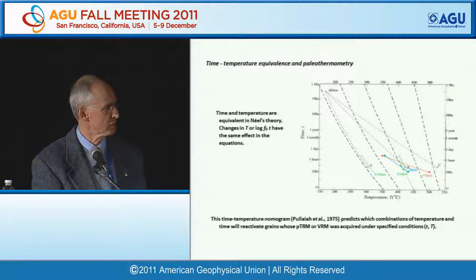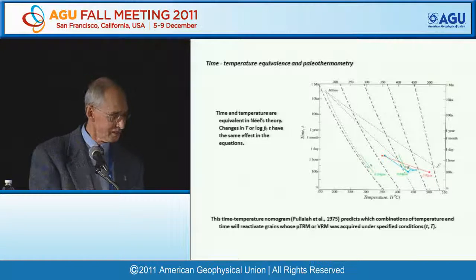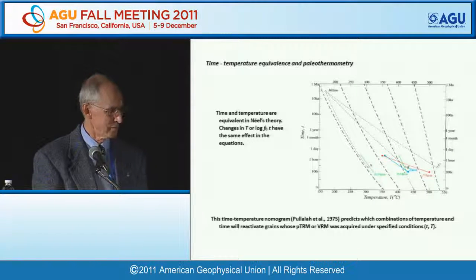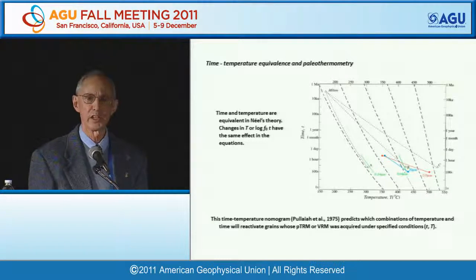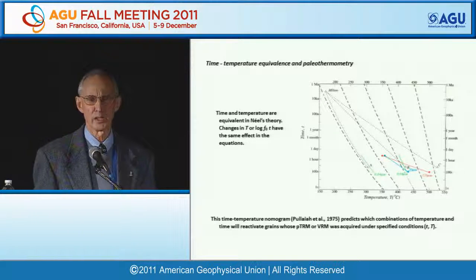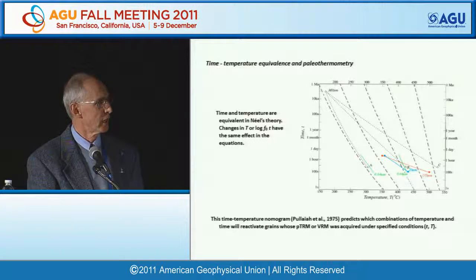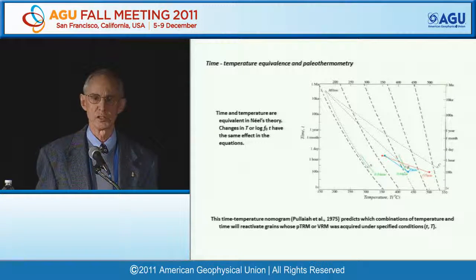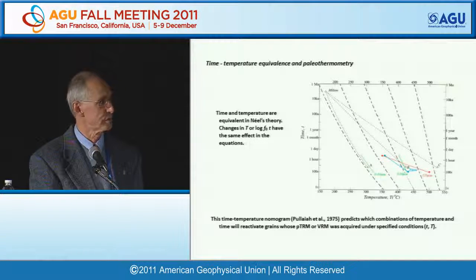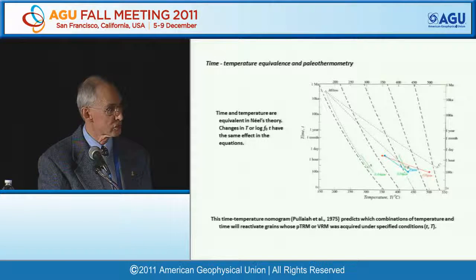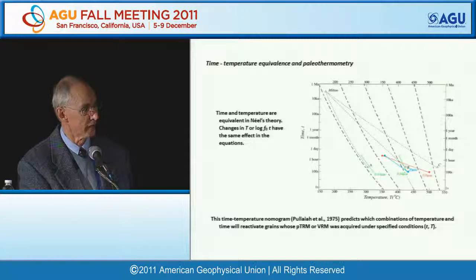So to take a concrete example, suppose that you produce a VRM at this temperature for single domain grains, which in fact is what we did. The temperature, I think, is about 280 degrees. And we did the experiment for a few hours, so that's how we got this point. Then heating fairly rapidly on a time scale of a minute or two, you could ask the question, how high do you have to heat in temperature in zero field to get rid of this VRM? Well, the experimental answer is up to about 320 degrees, and that is exactly what these Pullaiah contours, or Néel theory,